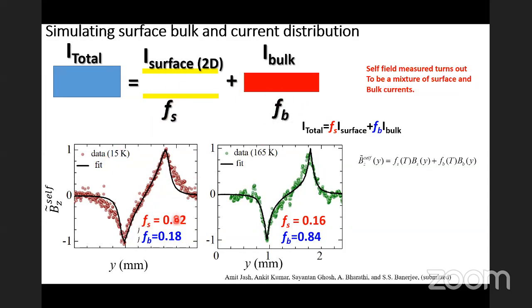So at low temperature, we get about 82% of the current flowing on the surface as 2D surface sheets, and only 18% through the bulk. But as you increase the temperature, this fraction completely reverses. You get about 80% through the bulk. Because of the presence of selenium vacancies, the bulk conductivity increases beyond a certain point, and you get the conduction through the bulk rather than through the surface. So the current on the surface decreases because more and more current starts channeling through the bulk, and this we see clearly.